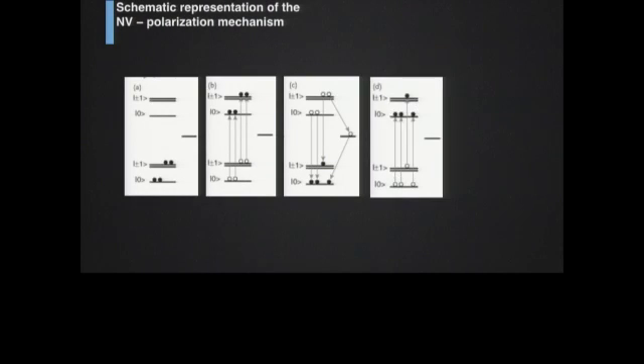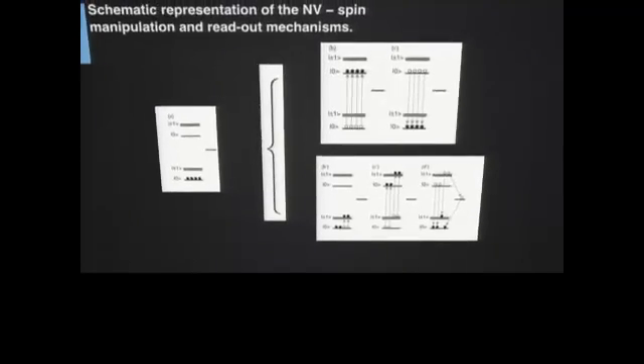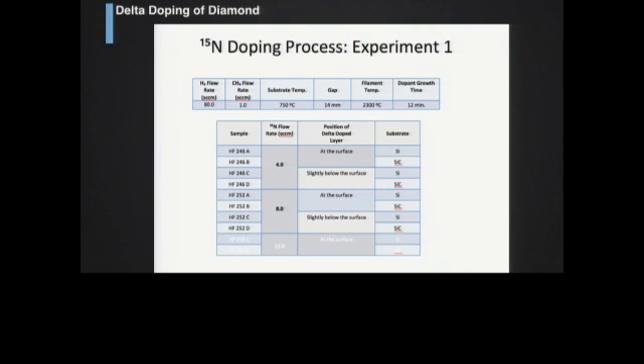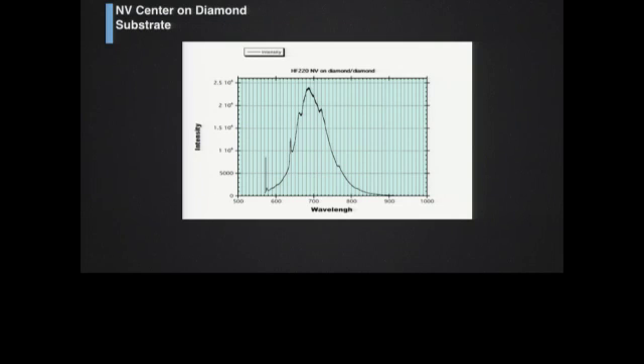I'll skip this. That just talks about the NV center. And this is just some of the growth parameters. We've done these super thin layers in silicon carbide, and at the surface, slightly below the surface, all different kinds of possibilities. Here's the actual fluorescence of the NV center of diamond that we grew on top of diamond. Marco told me this was one of the strongest NV centers that they've observed. And it might be because we primarily put it near the surface of the wafer.